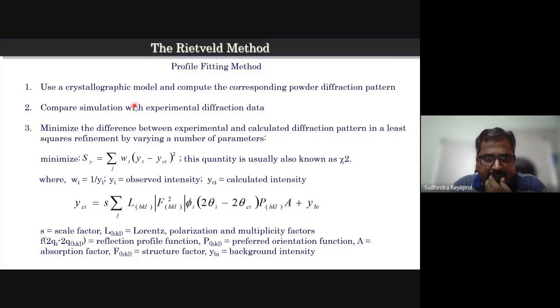Okay, so now coming to the method, what is actually the Rietveld refinement method? You are using a crystallographic model and we are computing a corresponding powder diffraction pattern. So based on certain equations, we are generating a diffraction pattern and we are matching it with the observed data. So we are trying to simulate the pattern. We are refining this model, the experimental model, which is there in the PCR file. So we are manipulating the information in the PCR file. We are refining the lattice parameters, the background, the atomic positions, and we are trying to match it to our actual data.